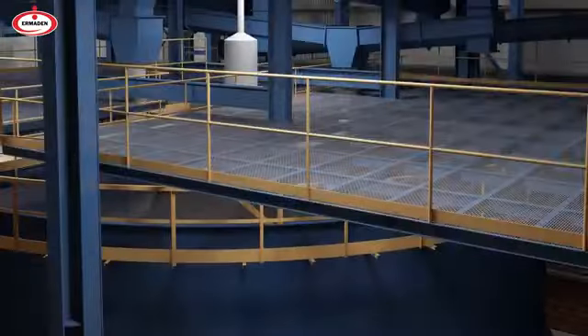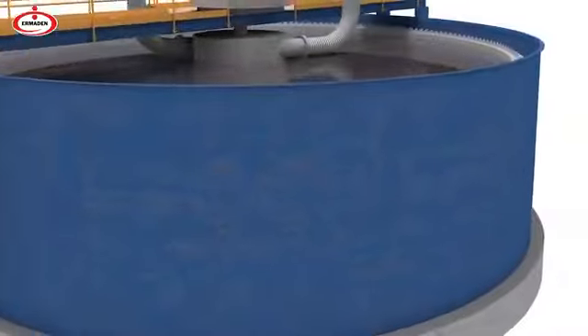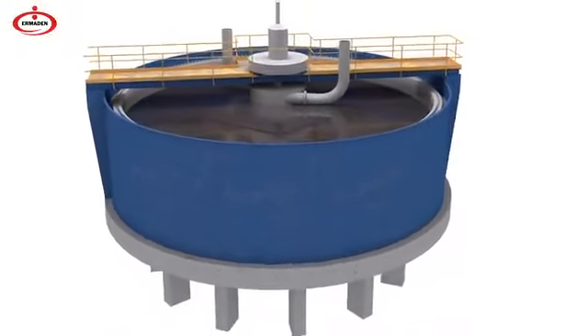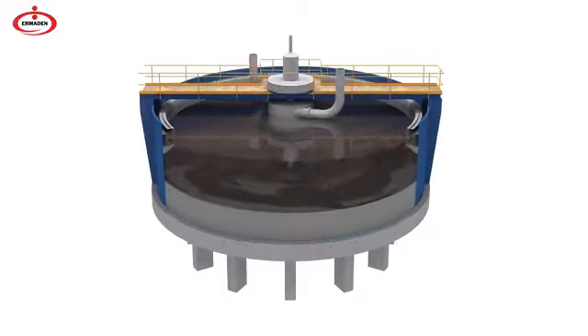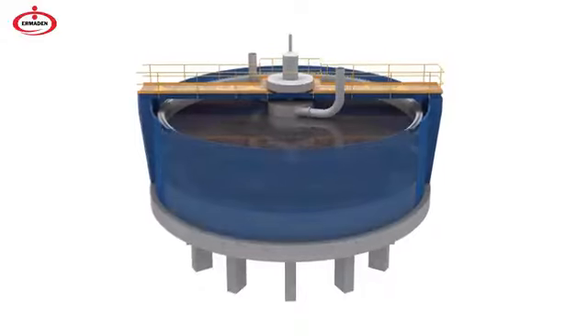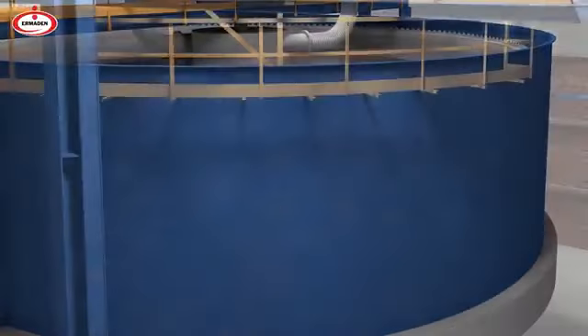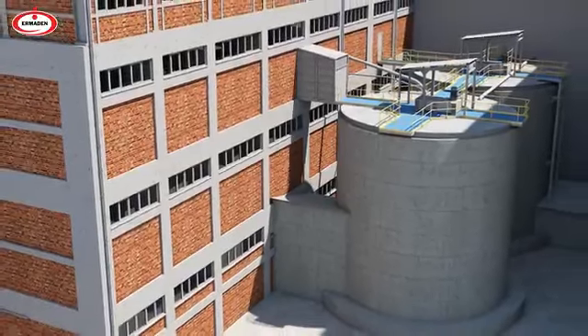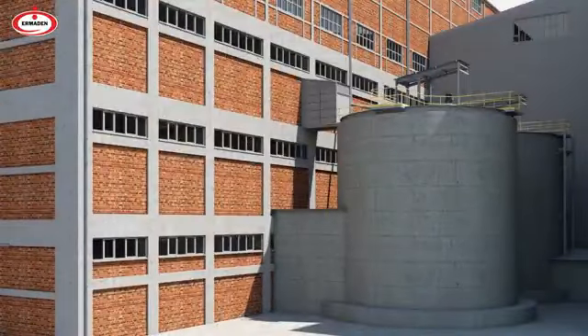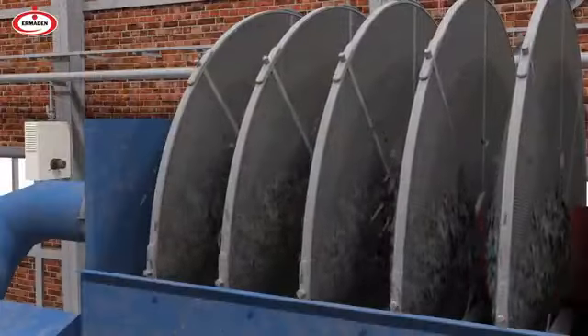The iron content of the filter cake produced in this way reaches 67%. After separation, the product is thickened in thickener units and taken into storage tanks. The ore stored in tanks as thickened magnetite sludge is brought into cake consistency by decreasing the humidity in vacuum disc filters, and it is sent to the mixing unit silo by conveyor belts.